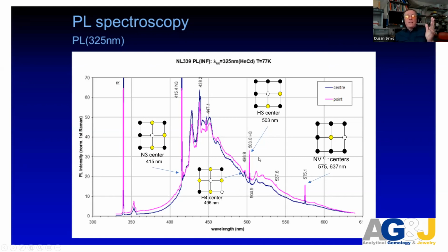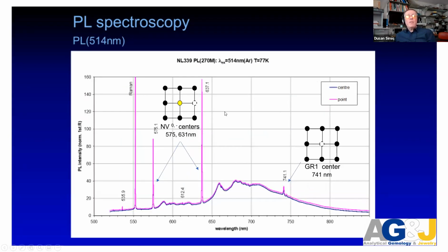So much information, and the most important information here is the presence of this line that is characteristic of centers that is characteristic for HPHT annealed stones. When we go to the 514 nanometer laser, we see something that, right now, is easy to say: when you see NV centers, when the 637 center is stronger than the 575 center, you will say, okay, this is HPHT annealing.